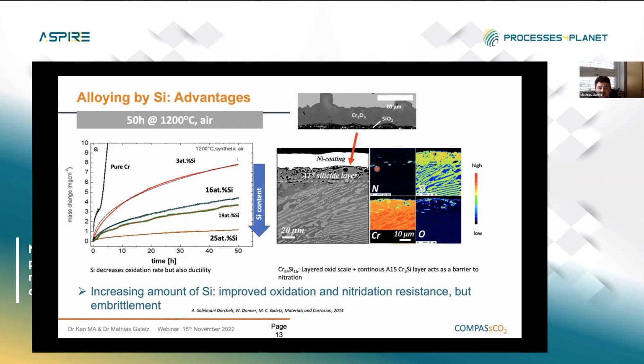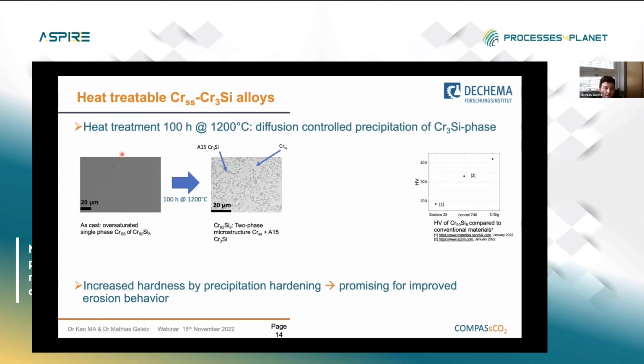Okay, let's go to the next slide. Here you can see the heat treatment at 1200. We have a single phase oversaturated as-cast microstructure. This is from alloy development, an arc melted sample. And then when you do a heat treatment, for example, at 1200 degrees C for 100 hours, you can see that you find small precipitates of this A15 phase.